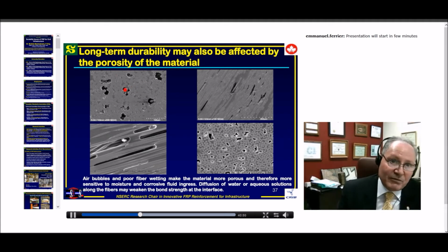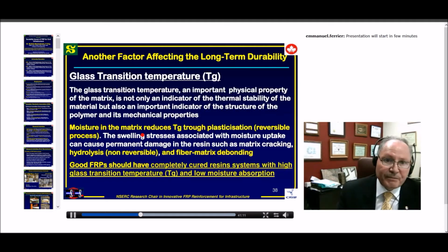Long-term durability could be affected, as I said before, by the porosity gaps, as you can see here, or by fiber impregnation, as you can see here. And this kind of defect you can find in as-received materials, so you have to look at it before really starting your testing and studies.